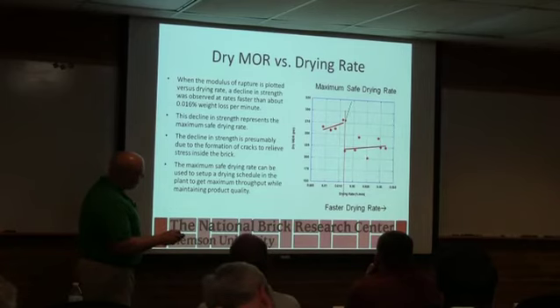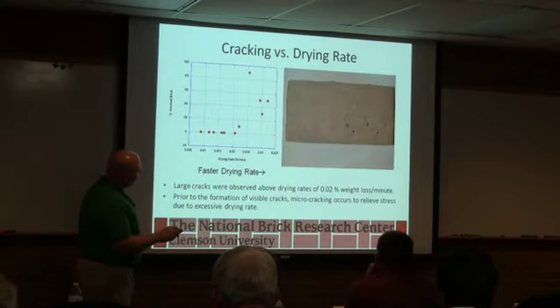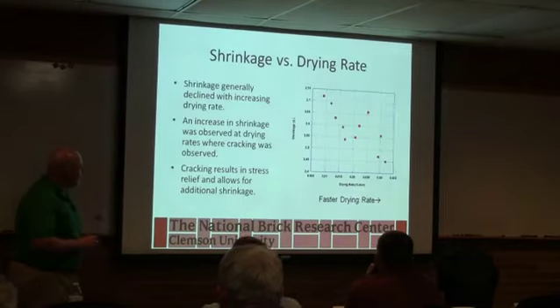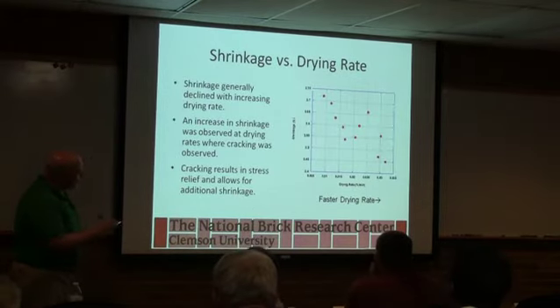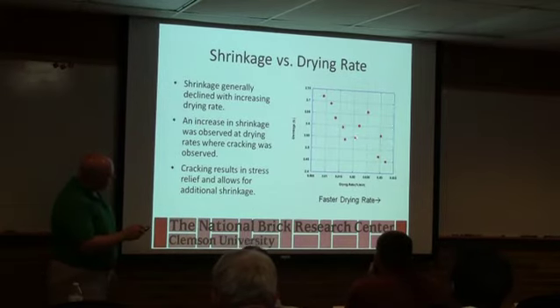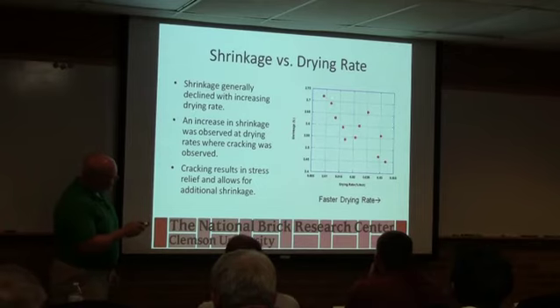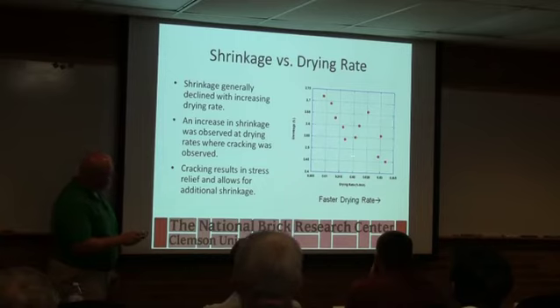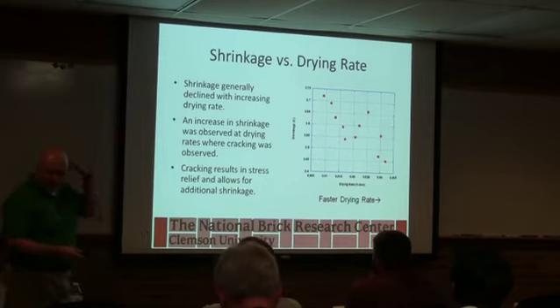So somewhere around 0.016% water per minute. We had to get out a lot higher before we could see visible cracks. And then shrinkage, what's interesting, until you get into this cracking period, basically shrinkage drops as we increase drying rate. And that's what we talked about earlier, about the particles approaching each other.